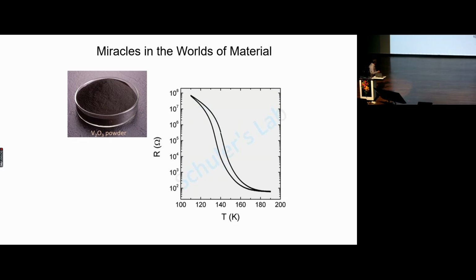But this same material, if you start to heat up, and you come to about 180 Kelvin or so, by room temperature, you see resistivity catastrophically comes down by 6 orders of magnitude, and there it begins to conduct electricity almost as comparably as copper metal. So this material, which otherwise is an extremely good insulator, just because of changing the temperature can become almost like any good metal. This is a subclass of material study, which is the metal insulator transition, which can be brought about by either pressure, temperature, or slight changes in composition, and again plays a very important role.